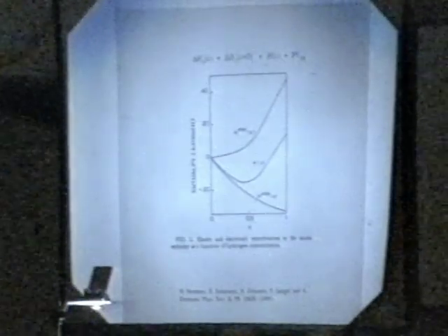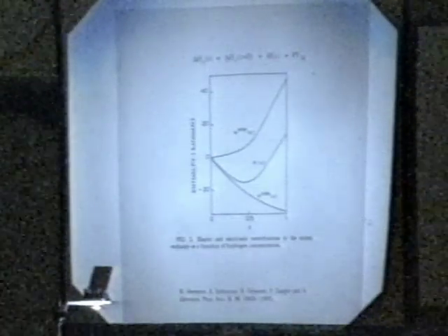Well, there's an extensive literature on this subject. Here we take, here's our quantity of interest. So, these authors here subtracted off a couple of more or less constant terms to leave them with this quantity here. It doesn't really matter what this is, it's just related to this by some constants. And they plot this quantity versus composition. So here's our elastic term, our favourable mechanical interaction with the lattice, decreasing more or less linearly with the load.